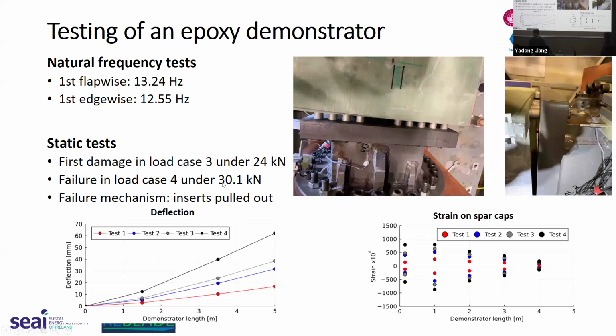And actually, it's not a failure of the composite material, because when we checked the strain, we found it quite small compared to the failure strain of the composite material. The real failure is the pull-out of the steel inserts, as you can see in these two pictures. That means the bonding strength between the steel inserts and the composite material is not enough. That's why when manufacturing the second demonstrator, we changed to a different connector, which is a T-bolt connector.